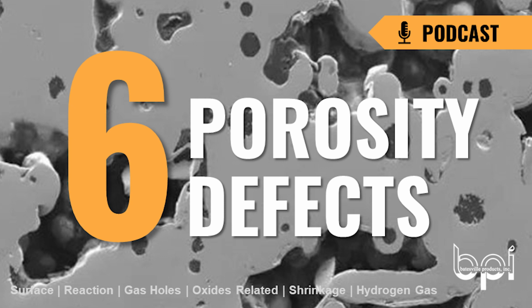So over 1400 degrees, I think it's every 100 or 150 degrees after that, the rate that the hydrogen enters doubles. Typically, that's why you want your casting temperature to be 1375, 1400 at the very top, if at all possible. Before you go on, the key thing: the hydrogen is soluble in molten aluminum, but it's not in solid aluminum. So as the aluminum solidifies, that gas comes out and forms porosity in your casting.